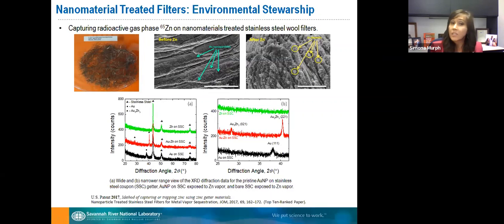And interestingly enough, they actually form an alloy with the zinc, which is really nice, because then it doesn't come off. And of course, as with any filter, how long can you maintain that filter so that it is still active? So we did a lot of studies looking into the retention and the stability of this nanoparticle and the loading capacity. And we also have a patent on this, and we published a few papers on this nanomaterial. So this can really be used for any other filtering devices with nanomaterials.